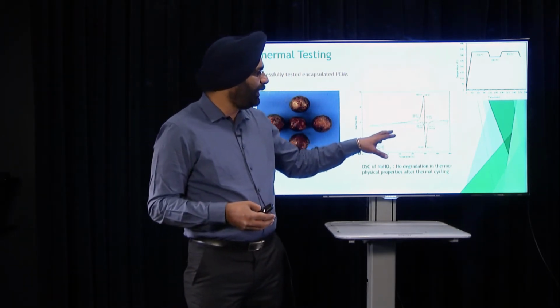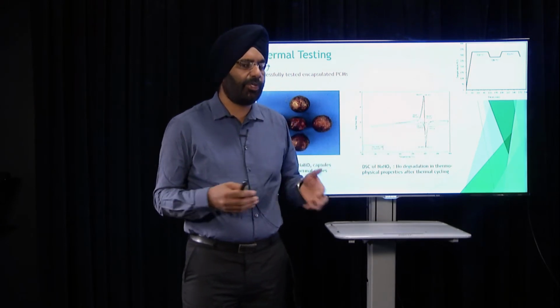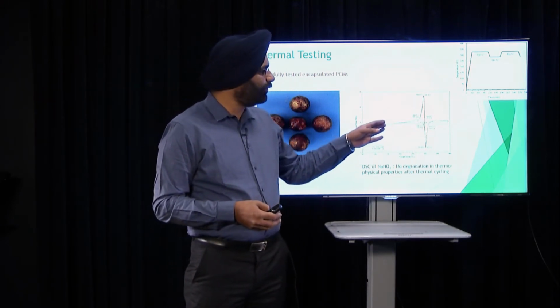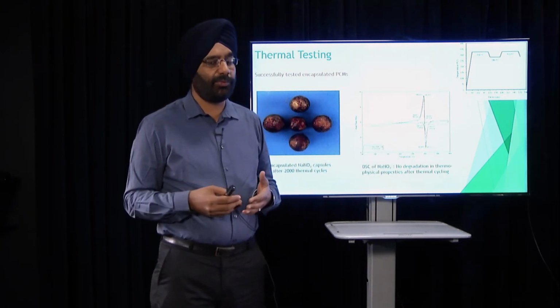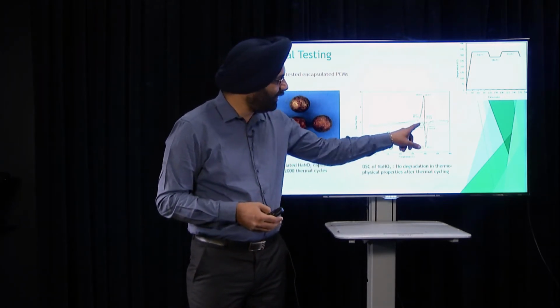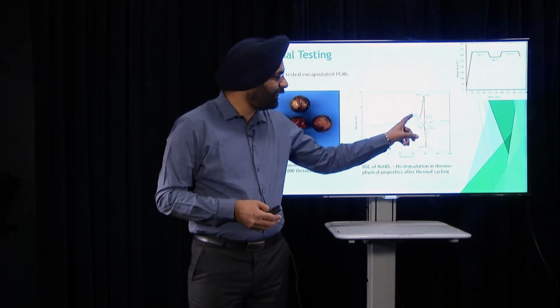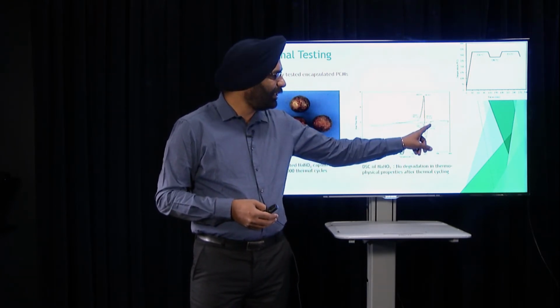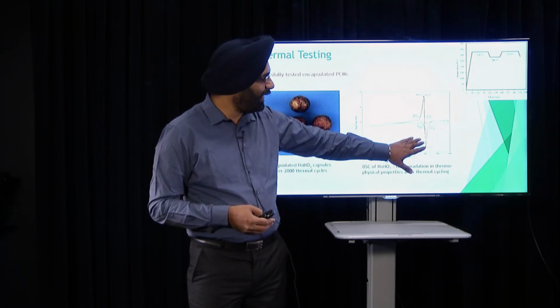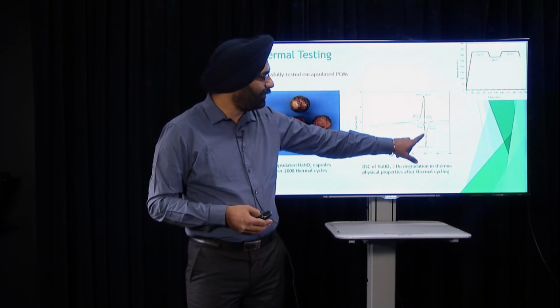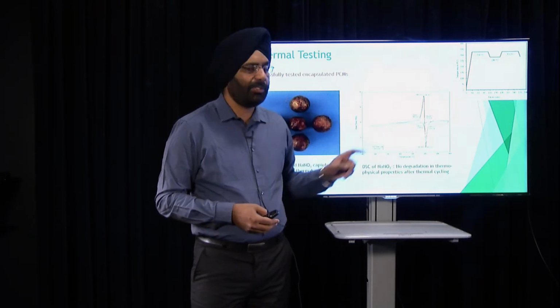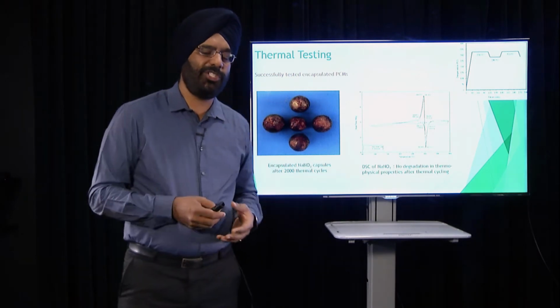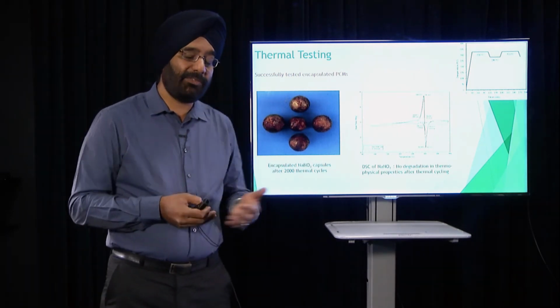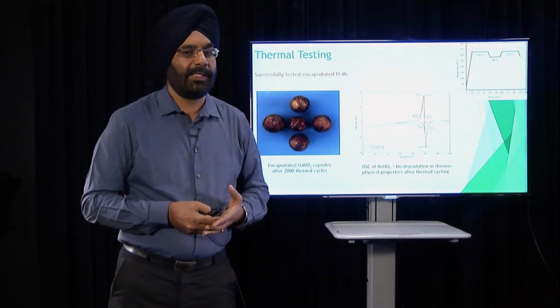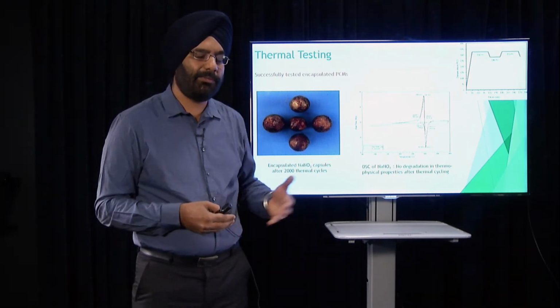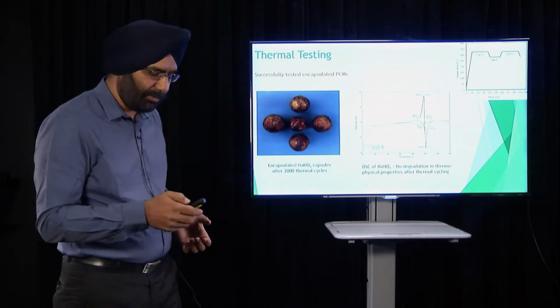There, we tested the as-received salt, which was not subjected to heating, and also the salt which was subjected to heating for more than 2,000 thermocycles. And what you can see is both the curves perfectly match. So there is no change in the melting point, and there is no change in the latent heat. This is called an exotherm. This is called an endotherm. This happens during the melting, and this happens during the solidification. So there was no change in the phase change material property after 2,000 thermal cycles. That also tells us that the phase change material is perfectly compatible with the storage material. There is no change in its chemical composition.